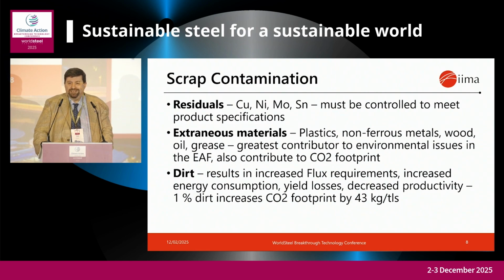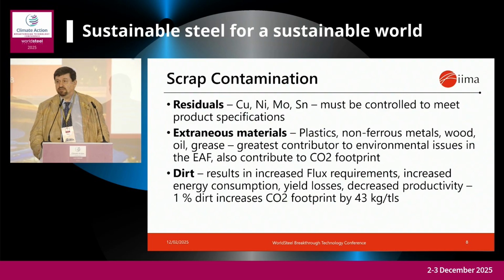It's supposed to make steel. So dirt, you know, is one that most people just don't seem very aware of. It increases your flux requirements, increases energy consumption and your yield losses, and it decreases your productivity. 1% dirt, when you look at how much flux you need to offset that, because the dirt tends to be acid gangue, results in an additional 43 kilos of CO2 footprint per ton of steel. For most people, that should be reason enough to take dirt out of the scrap.